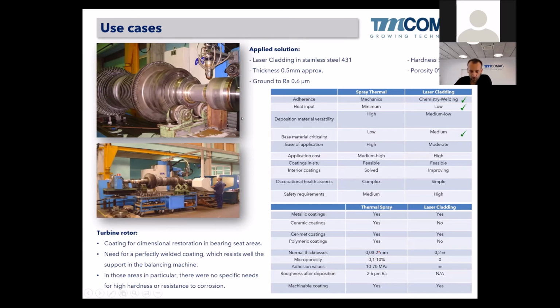Okay, so yeah, the applied solution was a laser cladding 431 again. It is our workhorse of laser for turbine repair. Thickness in this case was lower, 0.5 millimeters and so on. So here, why have we chosen laser? To avoid thermal spray coating delamination during balancing. Yeah, it's simple as that.